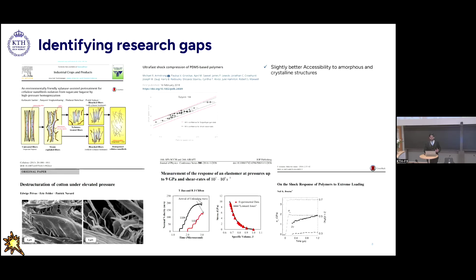So to sum it up, if we expose the pulp to dynamic pressure, we will have slightly better accessibility. We will have surrounding water, which is easy for pressure transfer as a pressure transfer medium. The current existing methodologies are a little bit energy demanding, time consuming, chemically demanding, and temperature degradation is a major issue in them. That's why, identifying all of these research gaps, we wanted to set up our experiment.